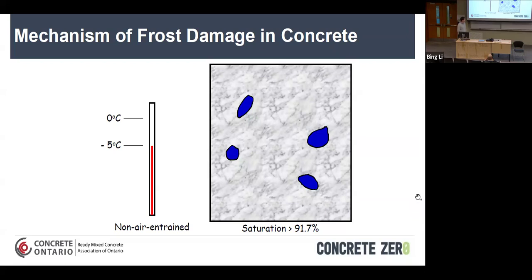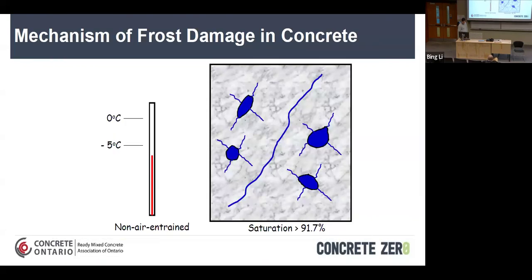It's a combination. Okay. Uh-oh. I don't like these lines. What happened? It cracked. Why did it crack? Because that water kept filling in the void, and eventually it was too much and it created a lot of pressure within that void, and it's trying to go somewhere. It's got nowhere to go. So it causes a lot of stress in the concrete and cracks start to form. I believe the reason why it's 91.7 is because water, correct me if I'm wrong, expands 9%. Yes. I thought it was 7 too. Okay, whatever, it expands. And that's supposed to be the number just above expansion.